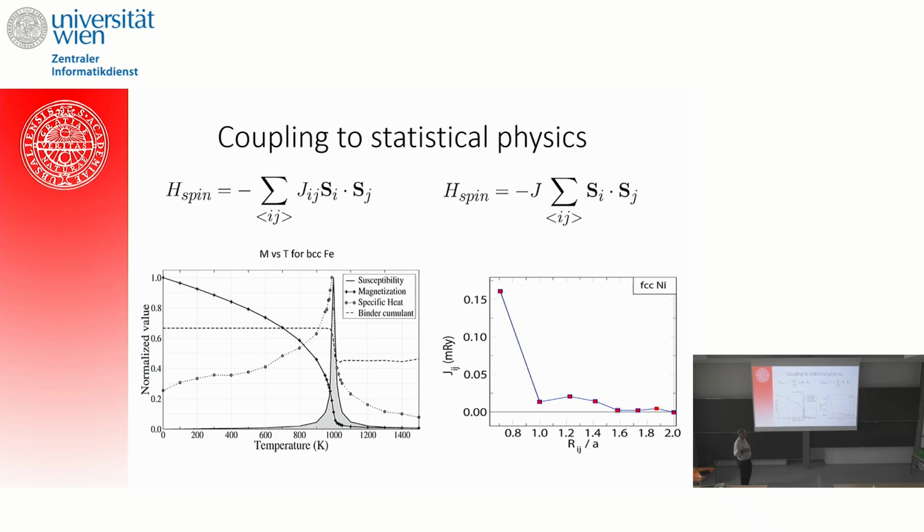And it continues. And asymptotically, this will turn into an RKKY-like interaction. Oxides, damped materials tend to have this one significant, and basically the rest you can forget about. Metals, that's never the case. So in metals, it's always a tail of interactions, at least when you look at these kind of calculations.